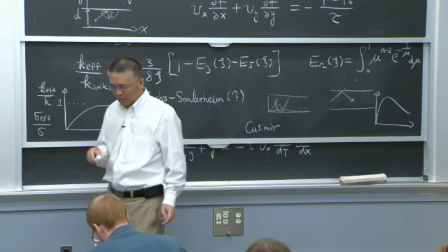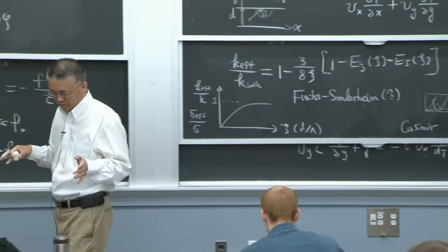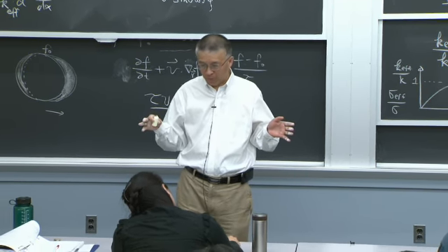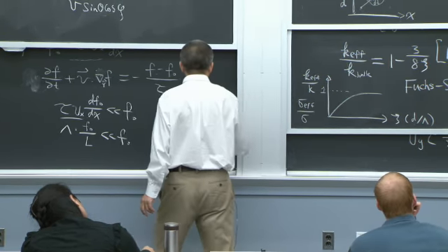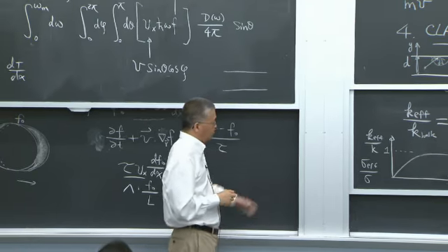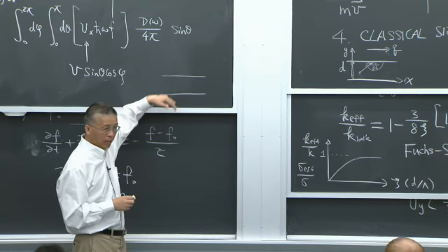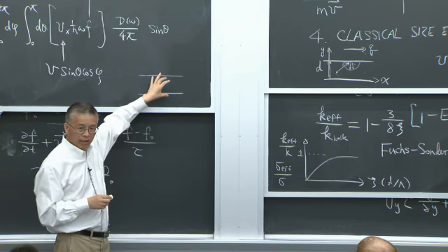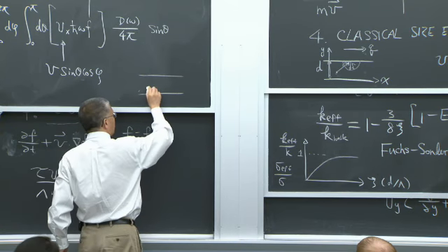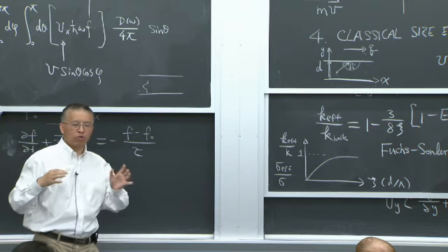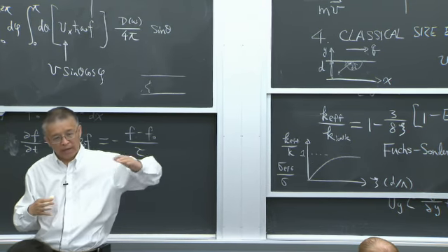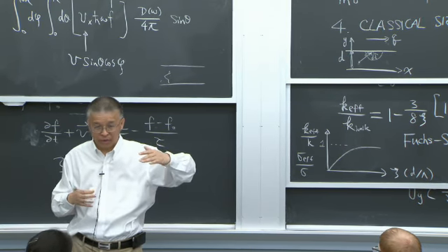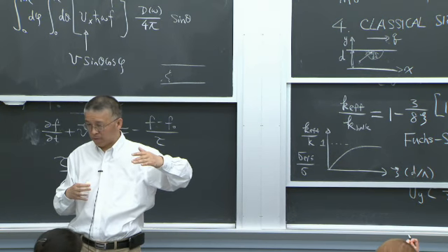One further comment: we're writing a paper on coherence, and I was thinking this weekend, where is this decoherence coming from? If I have a film, we're looking at the in-plane direction, but next I'll talk about the other direction. If there's no scattering inside, the phonon will propagate as a wave packet, so the phase is actually maintained. It's a coherent transport until it hits the surface.